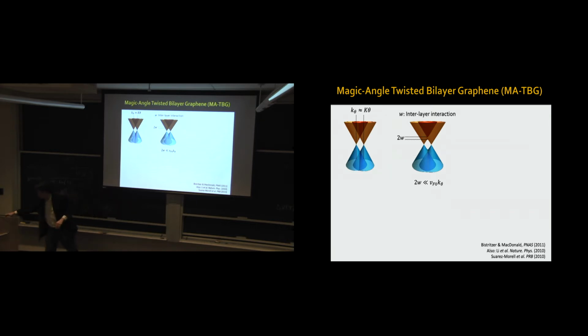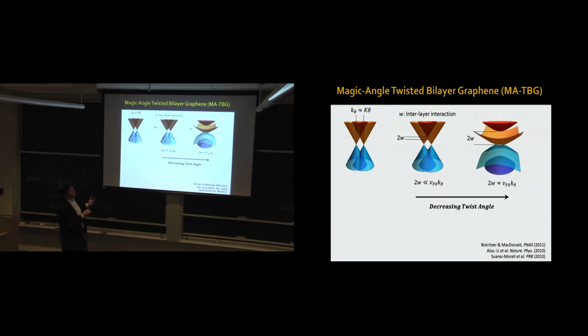If I keep decreasing the twist angle, I reach a value where the interlayer interaction is similar to where that crossing point is, so you form a flat band, pushing that bottom band down to 0. This condition is called a flat band condition, and it happens at an angle coined by Bistritzer and MacDonald as the magic angle. This magic angle value depends on the interaction between the two graphene sheets, and happens to be 1.1 degrees for graphene on top of graphene.